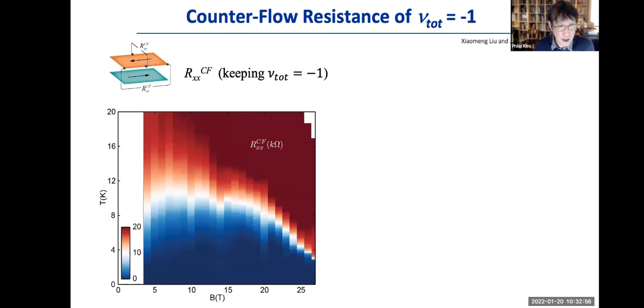Here, the magnetic field will control the magnetic exciton density because they are separated by the magnetic length scale. So as you increase the magnetic field, more and more magnetic excitons sit in and their distance becomes smaller. Therefore, you drive into the so-called BCS type of magnetic exciton states. Now, what you see in this data is that the blue color is where you get the zero counterflow resistance. This is the condensation state.